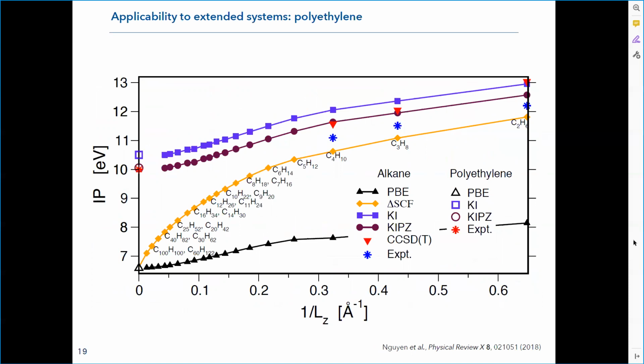Essentially, you remove an orbital from the system and you observe the relaxation. Then you can calculate the rescaling that you need between the unrelaxed pi parameter, the deviation from piecewise linearity, and the relaxed one. If you do that for an extended system, this entails calculating a charge defect in an extended solid, which is a non-trivial problem to address.